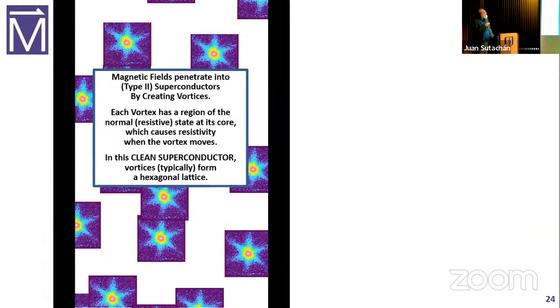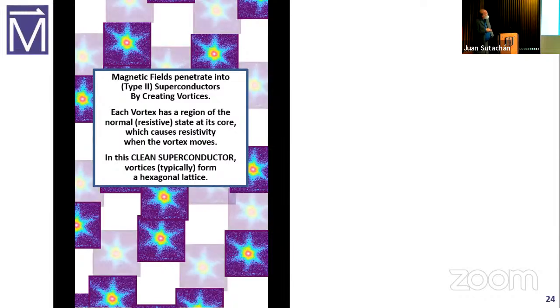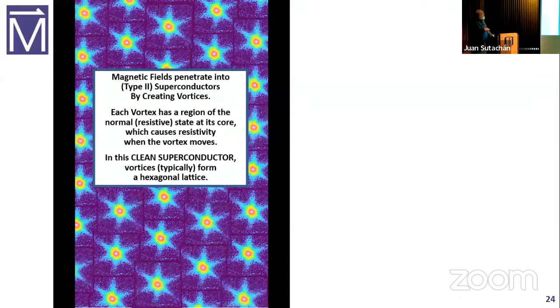Well, magnetic fields penetrate into a superconductor. This is meant to be the 2 sides of a tape that's kilometers long, going from way down there to way up there. When you apply a magnetic field, you get vortices that penetrate into the superconductor. And each vortex has this little white region in the center, it's not superconducting in the center. The superconductivity is in the blue parts. So as far as a conducting wire, it's perfectly good, but there are already some non-superconducting regions where the magnetic field has penetrated in. If you have a clean superconductor, the vortices typically form a hexagonal lattice, as I've shown here.